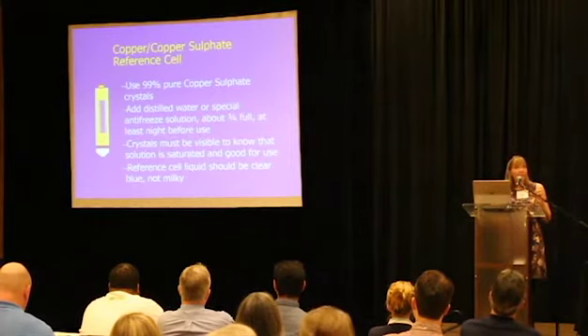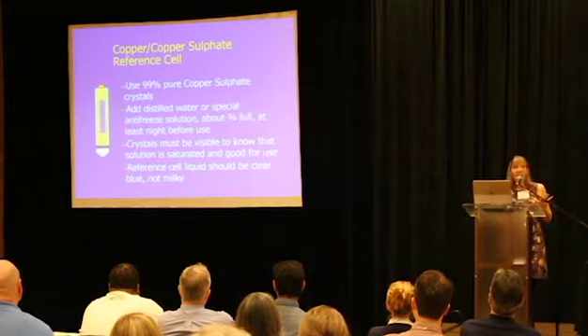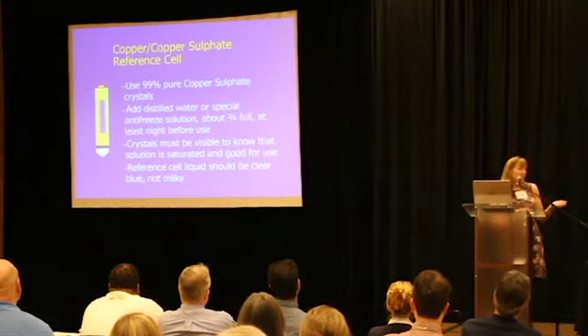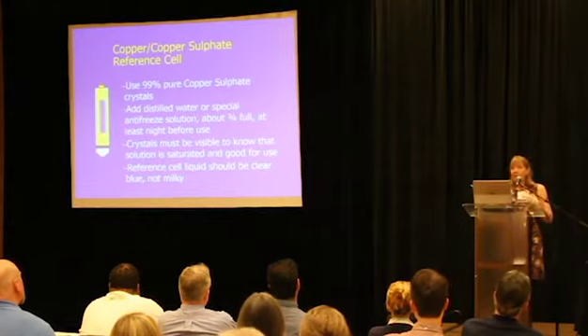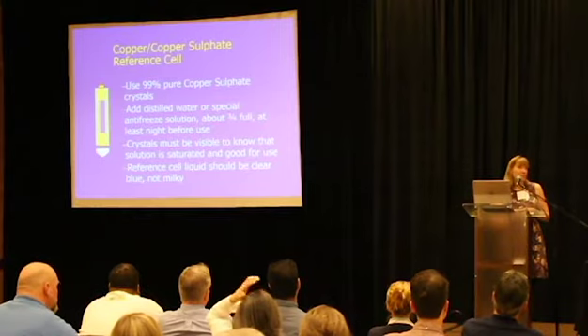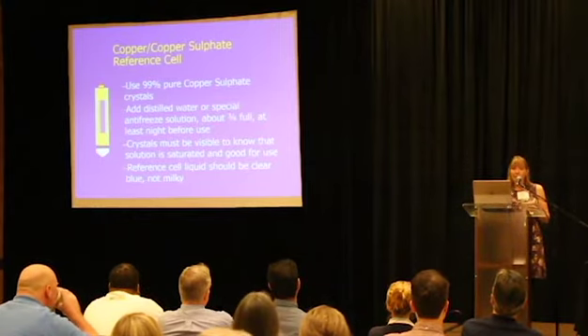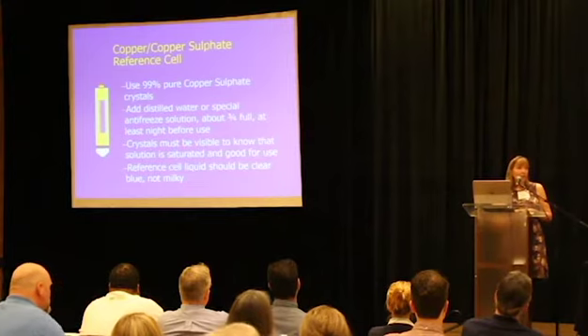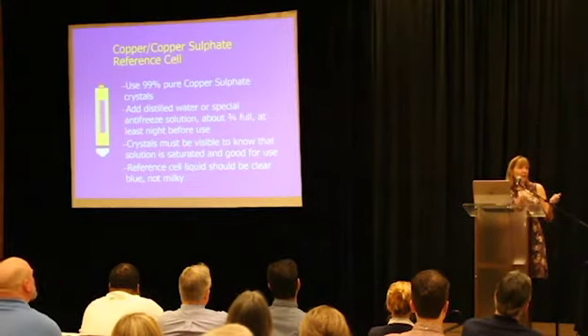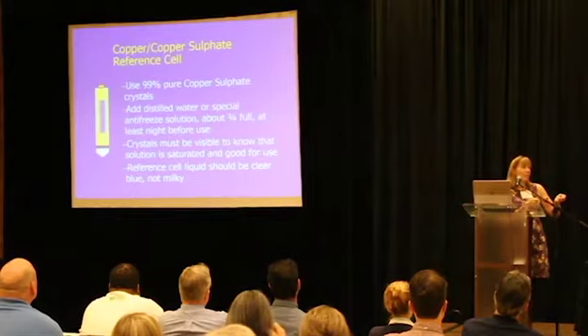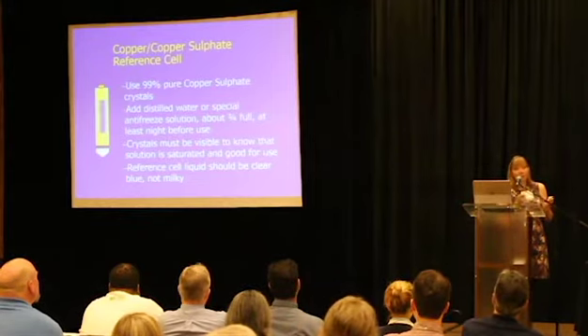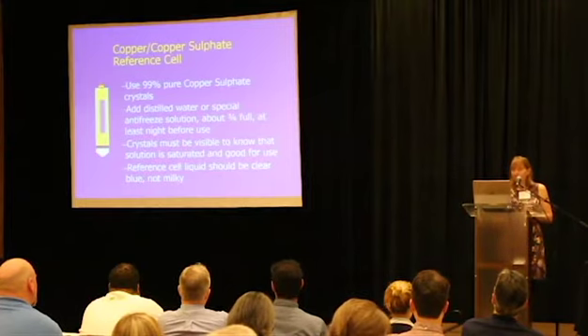And really important, because I've tried this a lot of times, it doesn't work unless you do this the night before. As I said, we go around and we teach these cathodic protection classes all around the country. We started using sealed reference cells after a couple of years, because these things were constantly draining all their water from being shipped around. We'd get there in the morning, fill them up with water, and they didn't really work very well. So now we use sealed reference cells. So it is important that they be recharged at least the night before.